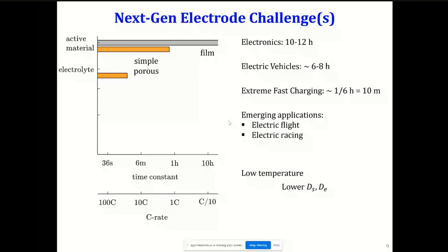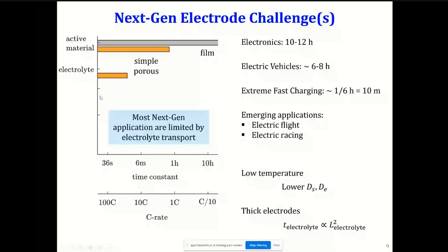Another opportunity is low temperature. So trying to start these batteries at lower temperature without any external device. And what ends up happening is your diffusions become sluggish for both the phases, electrode and electrolyte, as you go to lower temperatures. And it increases your time constants, and that's why you get worse performance than before. Another opportunity is thick electrodes, which increases the thickness of the electrode, which will substantially increase the electrolyte timescale. And the common denominator for most of this is that you're limited by electrolyte transport, right? In addition to being limited by solid state transport, which is the fundamental situation.